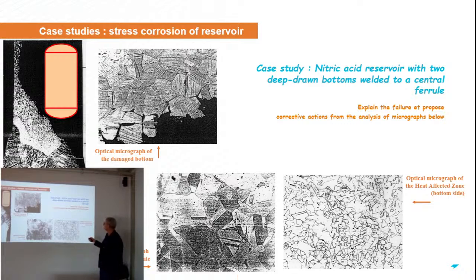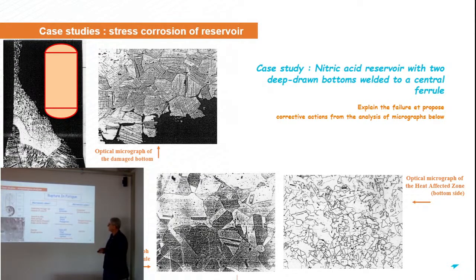So the corrective action here would be either to do the deep drawing process at high temperature so that you can have some recrystallization, what we call dynamic recrystallization, or doing the deep drawing at room temperature, which is the usual process, and then make a heat treatment afterwards to get what we call static recrystallization, doing the recrystallization of the grain after the deep draw. And in this case, no more residual stress in the deep drawn part, and no stress corrosion, probably. So this is a very simple corrective action here.